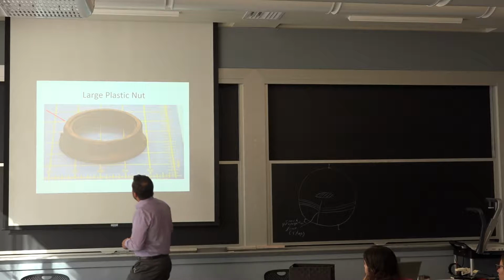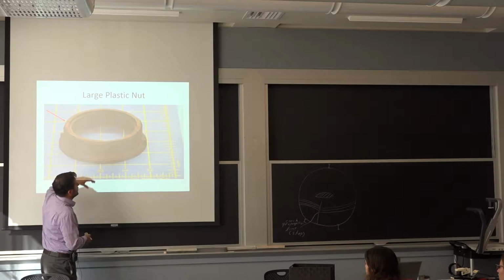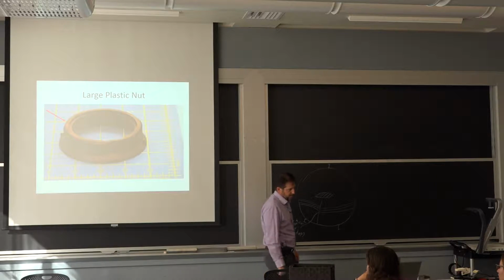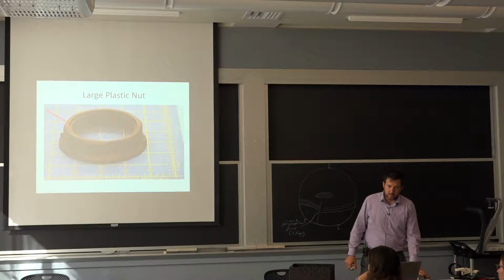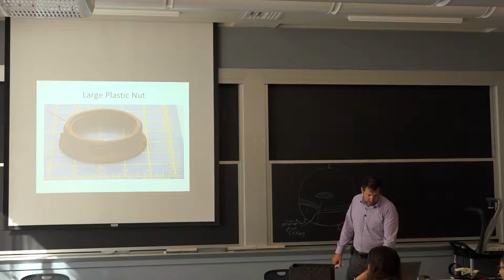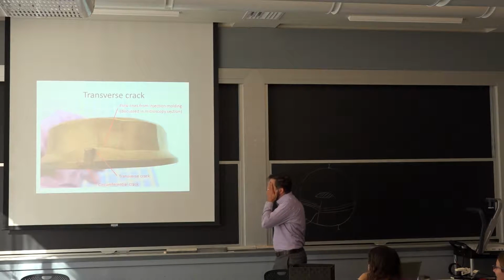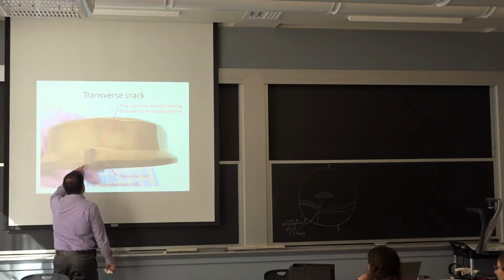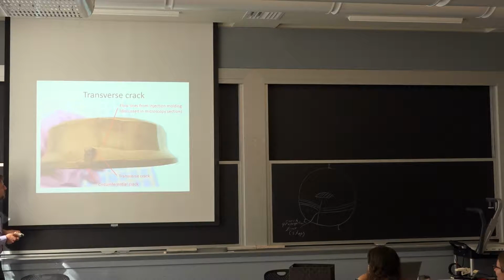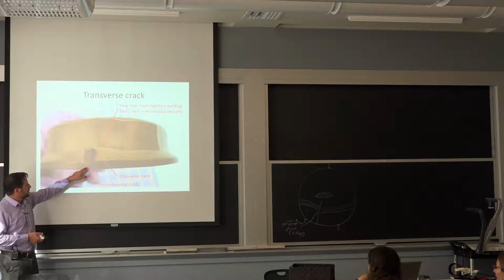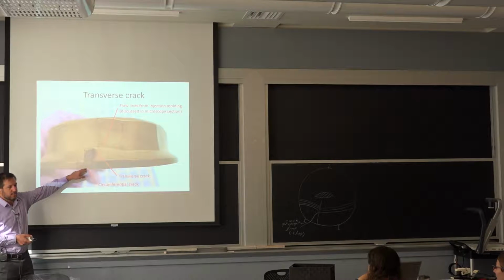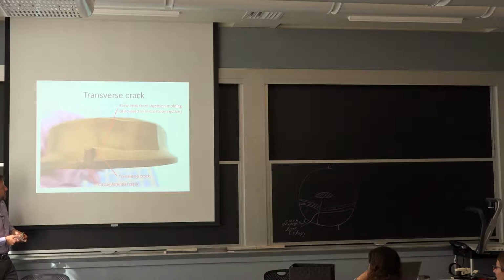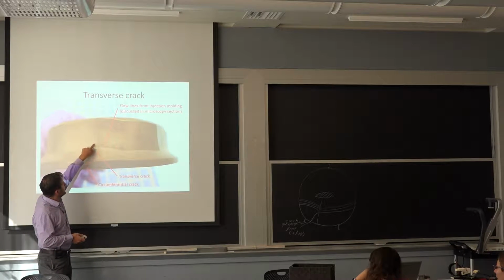This image didn't come out very well, but it's essentially a thread and nut that was used on a big exhaust system. It probably should not have been plastic, but somebody thought it was a great idea because it was corrosion resistant. So it was a composite, injection molded, and you can see this little tab. This tab had no reason to exist other than for the molding process. It essentially got damaged on this end here. Probably during service, there's no reason why they will cut that part out in the factory, and that's really where the crack started. So from analysis of this, we've looked into, the image is not really good.